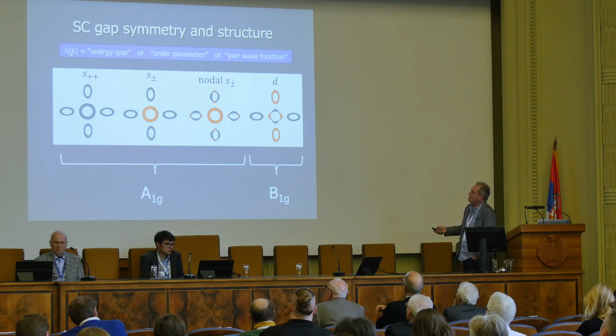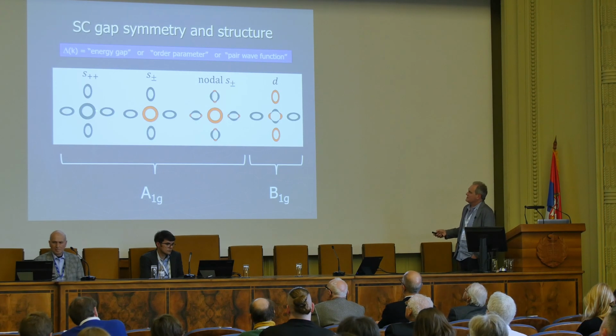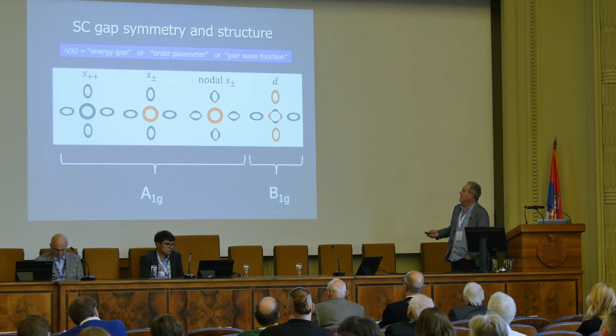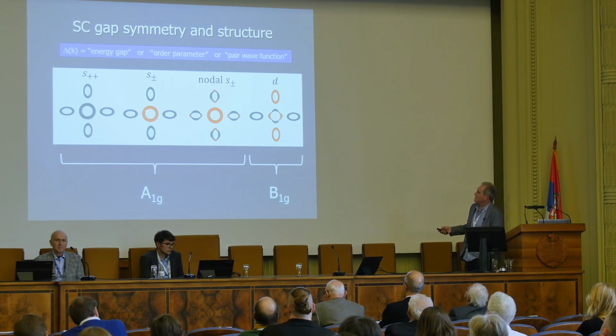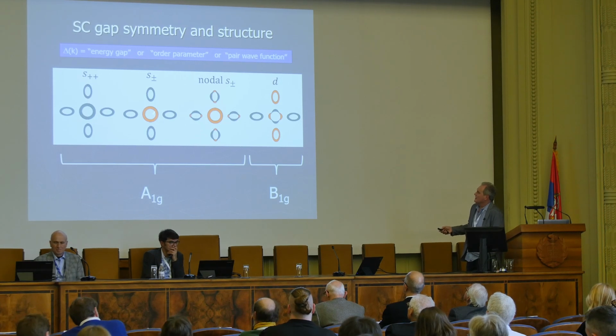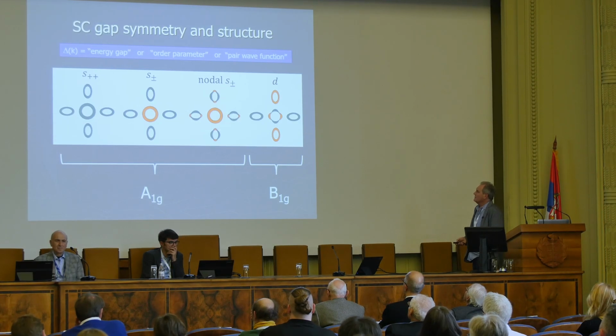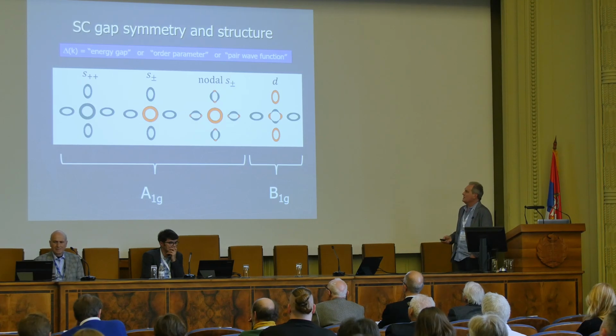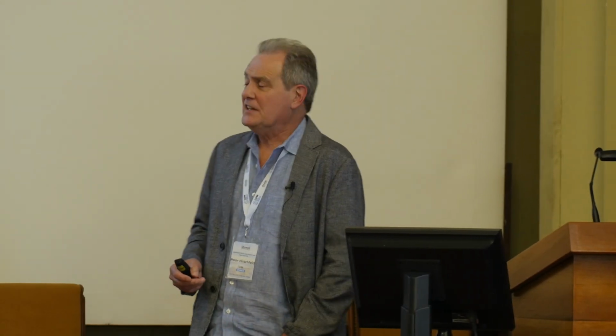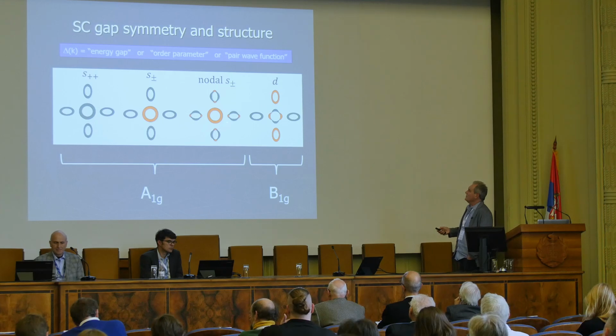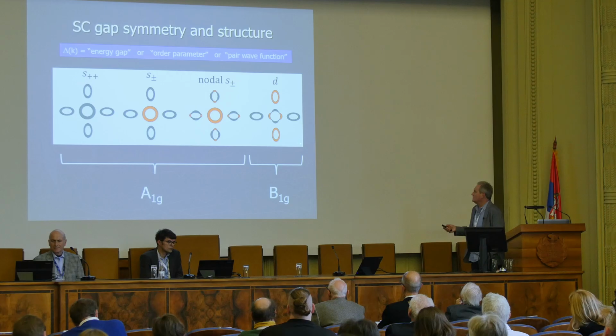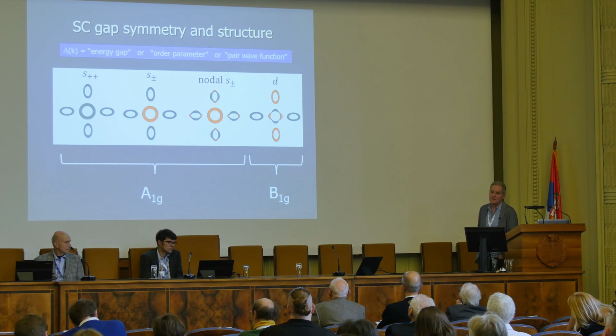And the color indicates the sign of the gap function. So if it's all green on the left, that says that on both the electron pockets and the hole pockets, the gap is plus. Whereas I could have S plus minus, just from a symmetry point of view, it's a possibility. I could have this gap with minus sign, okay? And then there's a phase change between these two inner and outer pockets. In principle, that also allows for subtle changes, which would allow for nodes on any of these pockets. But note that the first 3 examples that I show you here, they're all called A1G or S-wave states in the nomenclature. That's just because this is a tetragonal system, and if I rotate by 90 degrees or 180 degrees, this picture goes into itself. Okay, so there's no sign change under rotations. Whereas the last state listed here is a D-wave state, one of several possible D-wave states, which does change sign. Green goes into orange when I rotate by 90 degrees.